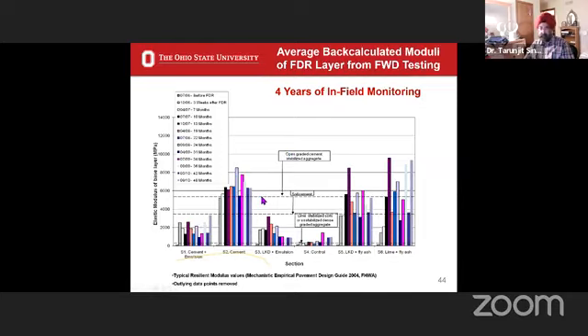But one challenge we have is we don't want our base to be so strong. If the base of an asphalt pavement is too strong, what happens? Reflective cracking. What we ideally want is something between these two values of soil cement and open graded cement stabilized aggregate. And that is where the fly ash or the CCB sections worked very, very well.